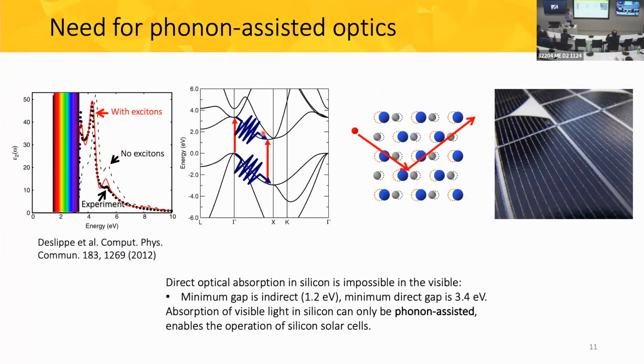In order for silicon to absorb a visible photon in the spectral region between its indirect and direct band gaps, we need phonons. Okay, the electrons need to collide with the vibrating atoms, get some extra momentum, and enable a transition across the indirect band gap. Just to make it clear, if the atoms in silicon could not vibrate, silicon would have been transparent, and you would not have solar cells.